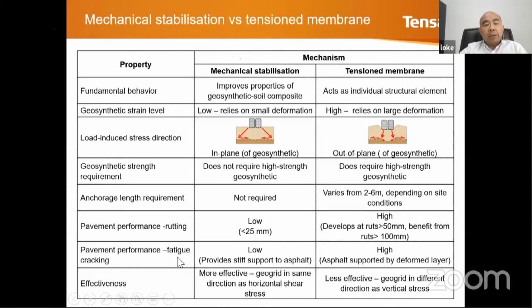Okay. Pavement performance fatigue cracking normally is very low. It provides stiff support to the asphalt. So the base course material is very strong. That's why it's required to provide stiff support to the asphalt. For tension membrane, asphalt performance is supported by deformed layers. So the fatigue level is very high. Asphalt cannot be supported by a deformed layer because the asphalt will already crack. Effectiveness: more effective with geogrid in the same direction as horizontal shear stress, or geogrid with higher strength, and less effective with geogrid in a different direction from vertical stress. So you can see that the geogrid is more effective in the same direction as the horizontal shear stress. Okay. So this is a summary between mechanical stabilization, or we call it stabilization, versus the mechanism which is tension membrane.